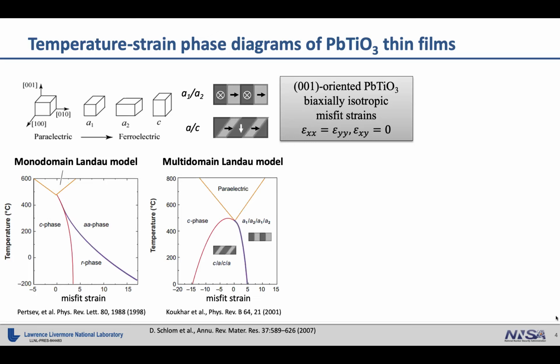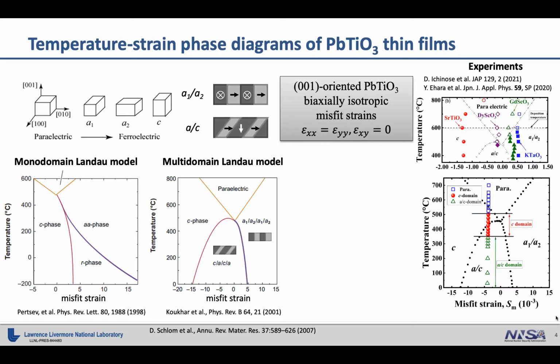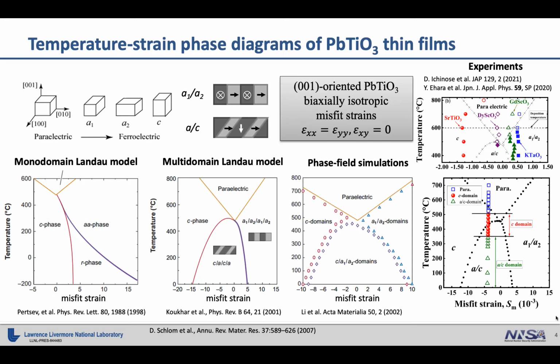Otherwise, they can also assume some simple domain structures and, based on Landau theory, predict phase diagrams. This one gives reasonable agreement with experiments, especially for the ferroelectric phase transition temperature, but they are slightly off when predicting the ferroelectric transitions at low temperature. And one of the state-of-the-art approaches is using phase field simulation to explore this strain and temperature space, which can give you a qualitatively good match with the experiments, which is impressive.